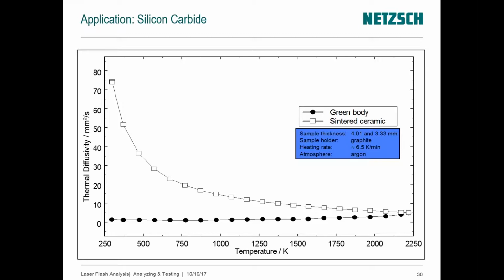We increase the temperature slowly. Along the way, there will be some occurrences as the binders burn away and things like these. And at some point, the sintering temperature will be achieved, and then the conductivity, the diffusivity will increase more and more, and will increase significantly. So essentially, we go from room temperature to 2000 plus degrees, and then keep measuring on the cooling side. So we went from room temperature to maximum temperature, and then we did all the measurements represented here with the dots.